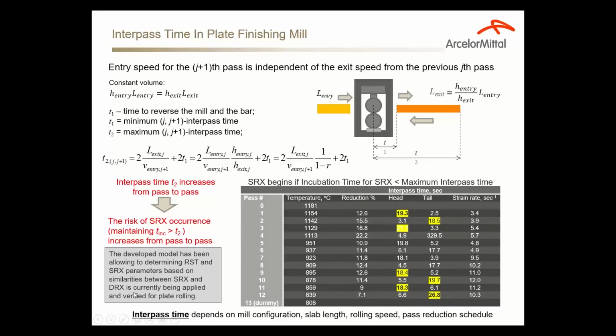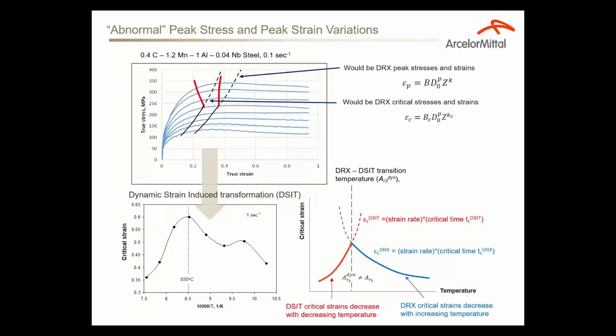Again, we are trying to use our model. It's still under development. We have positive, promising results from the plate mills as to preventing static recrystallization between the passes. Unfortunately, the only criterion here is measuring the final progress of the plate and looking at microstructure after transformation.